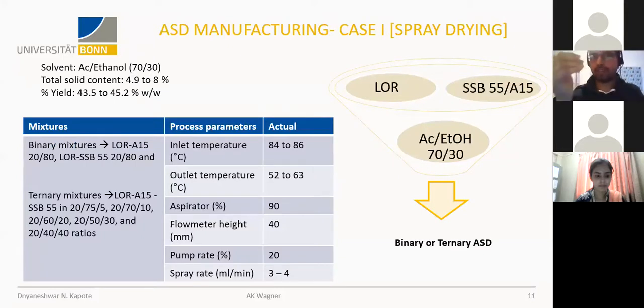Then, how to manufacture. The first case study was using shellac for spray drying. In this, we did preliminary screening, which is pretty important for spray drying. In spray drying, you dissolve the API and a polymer in an organic solvent or a water combination, whichever it may be. The API and polymer should form a homogeneous solution. This is the most important criterion. Then you subject it to the spray drying process, where the liquid is sprayed into the drying chamber, atomization takes place, and a fine mist is created. This fine mist leads to the formation of a powder, and the material goes from crystalline to amorphous form.